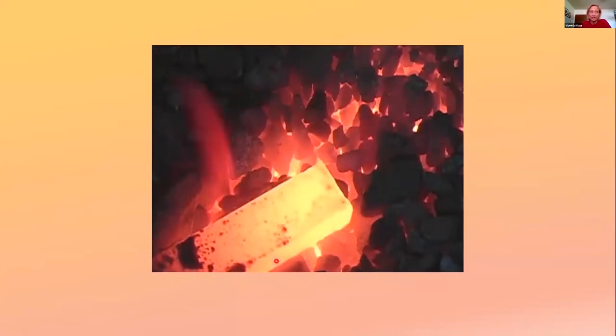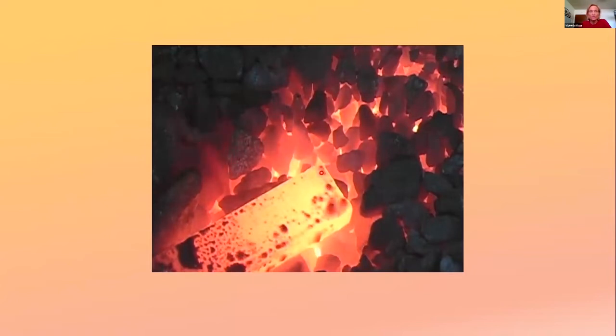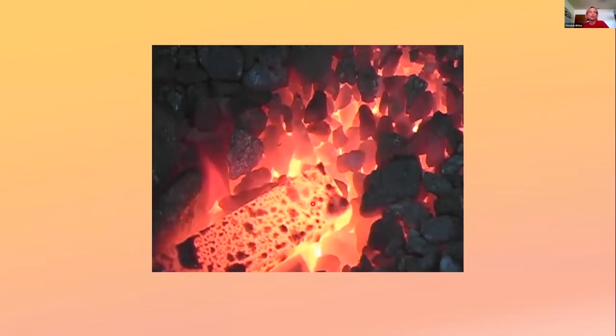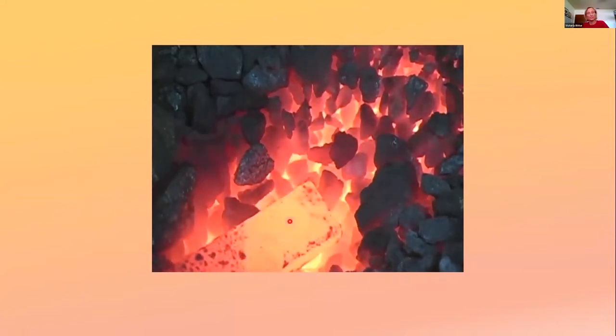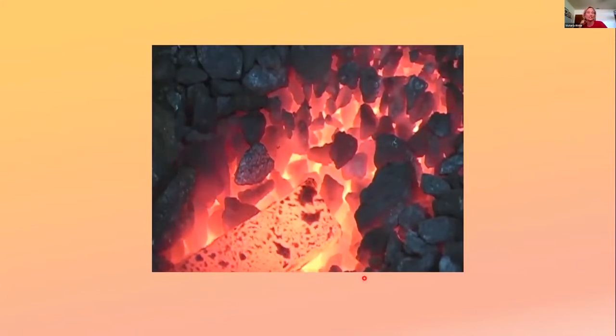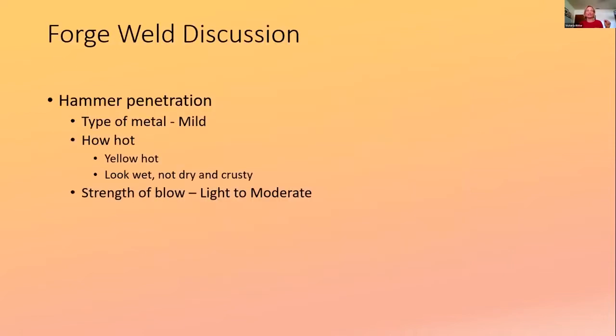As it cools, and this is just taking a second or two, you start getting this crusty, dry look. That crusty, dry stuff is oxidation or scale. It's dirty and it won't weld. Anything that looks like this won't weld. The other side of this is still a little runny, so we're still at welding temperature, so we get to watch that transition from wet to the dry, crusty part. That's how long you have to get your pieces positioned together in the correct alignment to forge weld them. Everything we do is to maneuver the pieces within the time window of having that yellow hot heat.